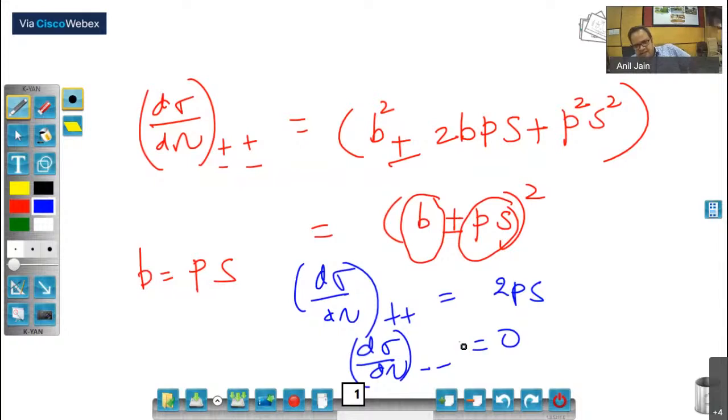So I need a crystal for which the nuclear scattering length and magnetic scattering length are equal. Suppose this is such a crystal, and I work in a condition where my Q is perpendicular to the initial neutron polarization P naught. In those cases, I can easily get this polarized neutron beam by using these crystals. And what are those crystals?